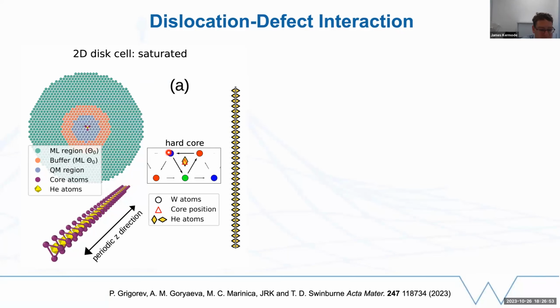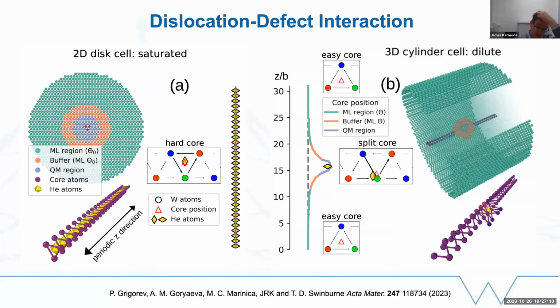And it had been reported that this leads to a change in the dislocation core structure. When you add helium, in this case, into the core, so you move from one of these upward pointing easy core configurations to a downward pointing triangle, a hard core configuration. But actually, if you study the more realistic case of a three-dimensional simulation cell far away from where the helium is, of course, the dislocation line stays as it was before, and it's sufficient to treat that with our updated QMML model. Close to the dislocation line, we do see some changes. It doesn't actually go all the way to the hardcore because of being constrained by the rest of the dislocation line, and we instead see an intermediate split core configuration.